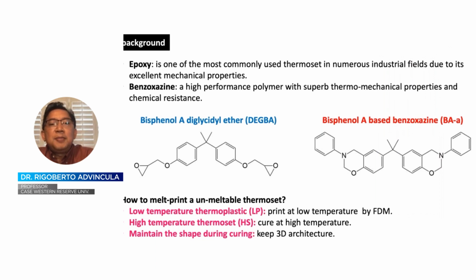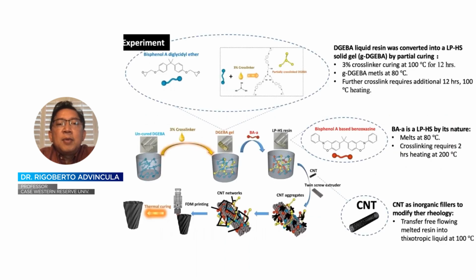So the chemistry we use is based on the reaction of DGEBA, a diglycidyl ether, which is quite popular for making epoxy, and then bisphenol A derived benzoxazine. So we synthesize this special monomer. What it does is that the benzoxazine is capable of copolymerizing with the epoxy, such that we can 3D print these two starting materials at a slightly elevated temperature, and then finalize the cure, and by keeping the shape as it was 3D printed, will enable shape memory materials.